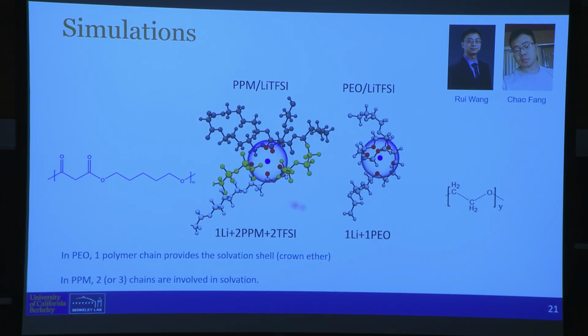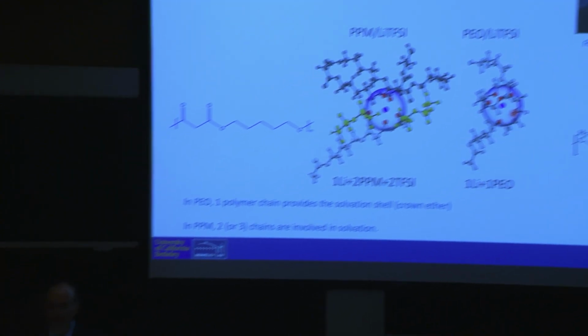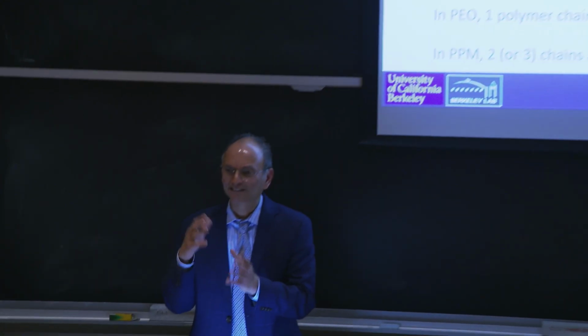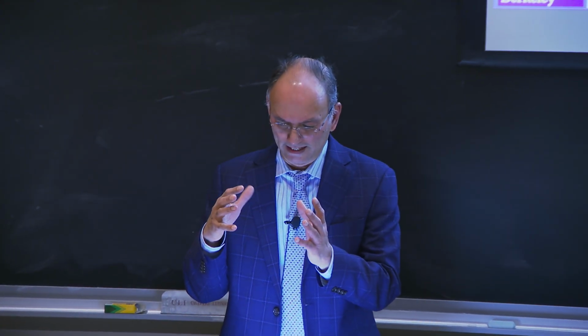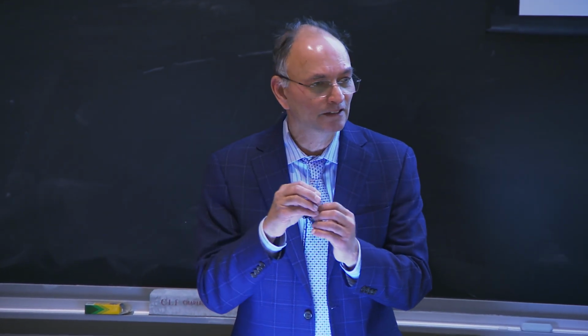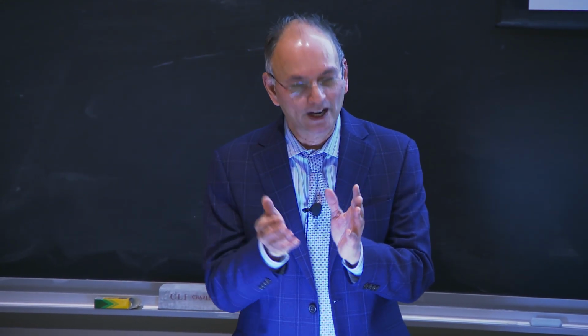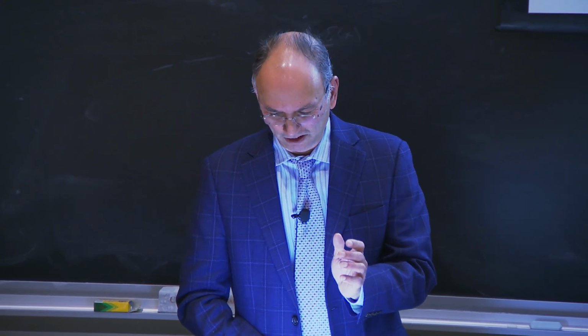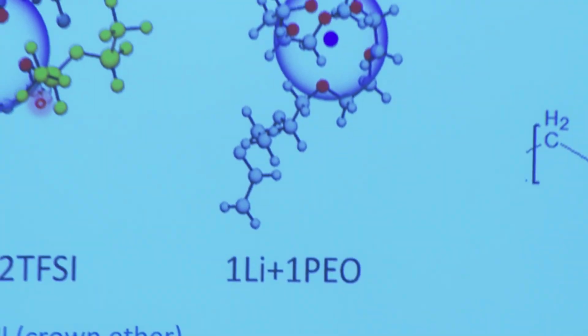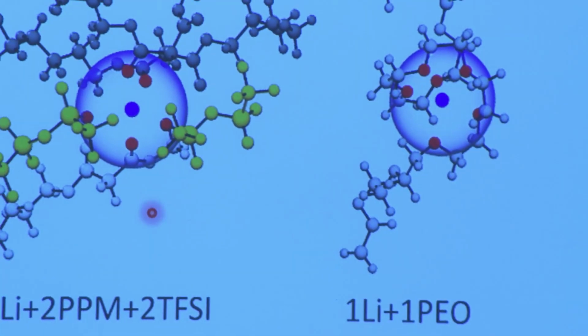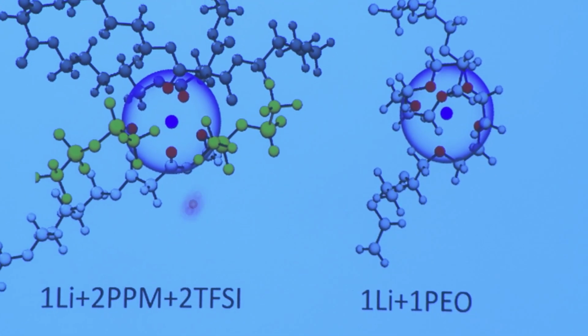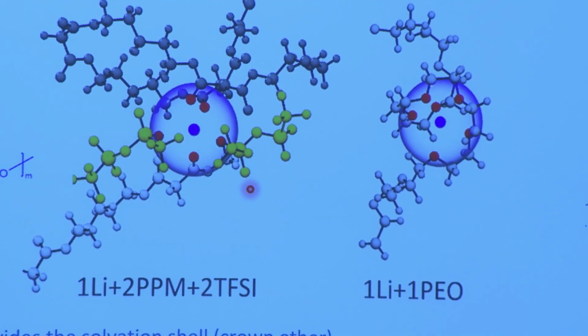And here are typical structures shown. What happens in PEO is that, you see, each ion wants to be surrounded by roughly 6 oxygens, whether it comes from water or the polymer. That's the number, not 25, for example. And in PEO, in most of the configurations, this is provided by one chain. Okay, so there's this gray colored chain that is all wrapping around this central lithium ion. In PPM, we have colored 2 chains because at least 2. Okay, and some of the oxygens are even recruited from the anion, which is colored yellow.